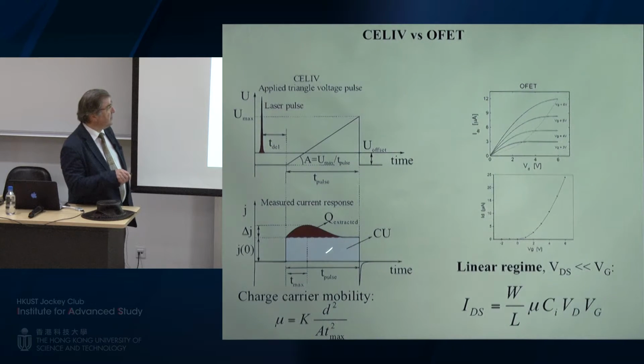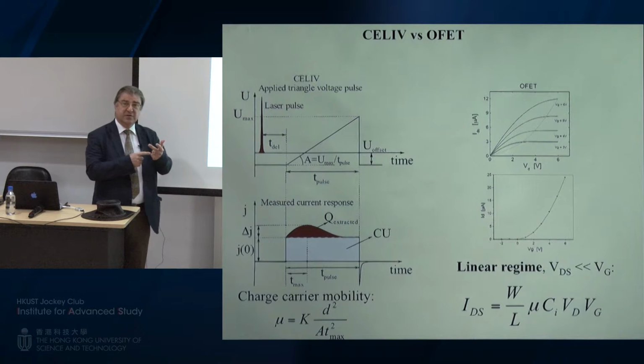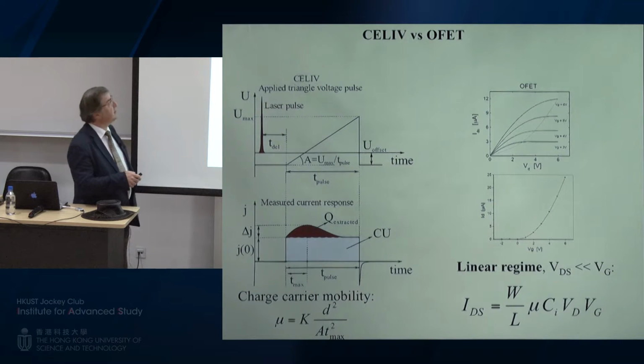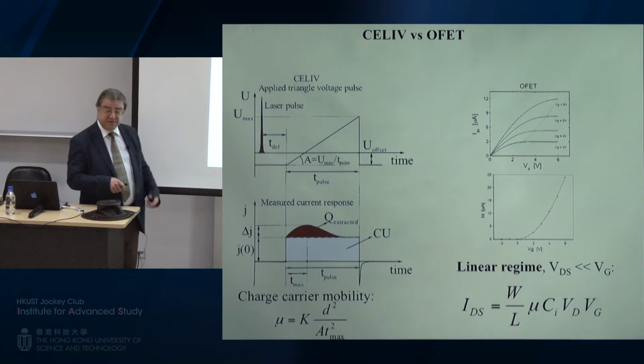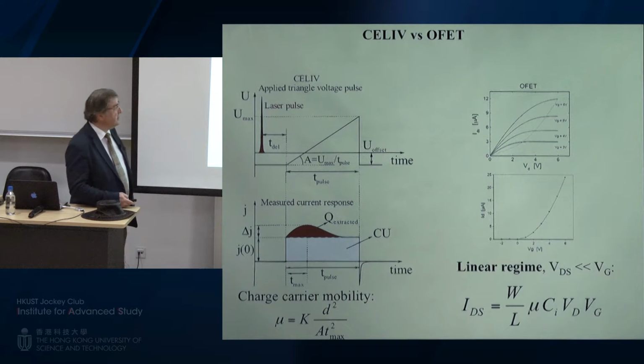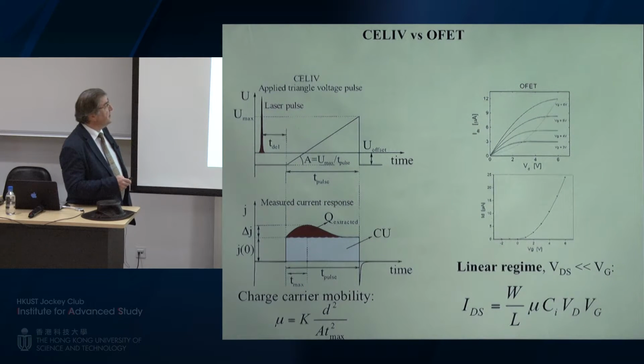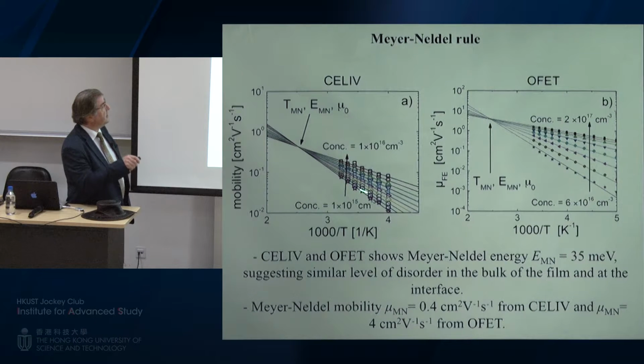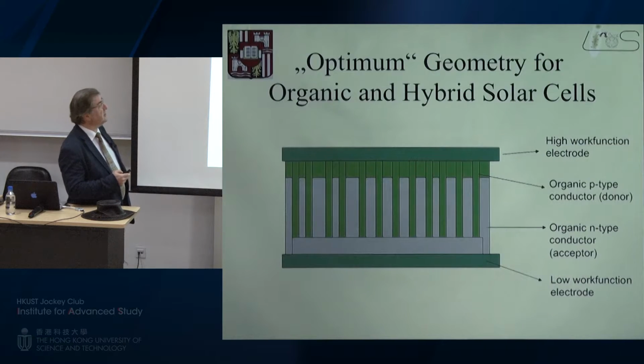In the diode configuration, I recommend very much the CELIV system. This is called charge extraction by linear increasing voltage, so it's abbreviated as CELIV. This CELIV is indeed a diode configuration, and it is a very good method to do these kinds of mobility experiments. And indeed, you can see this is very much activated, Arrhenius type of behavior. And there are very funny effects in these systems, like Meyer-Neldel points. These are details, but if somebody has questions, I can come back.